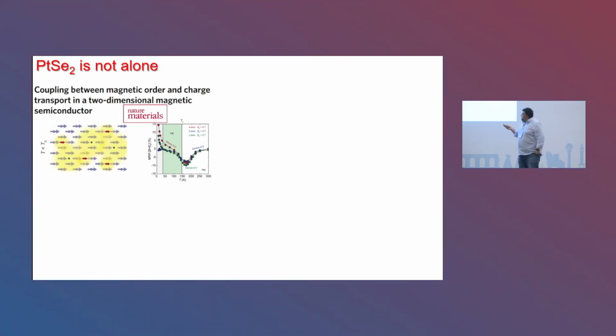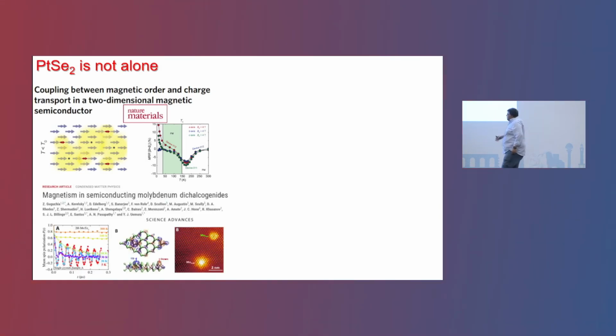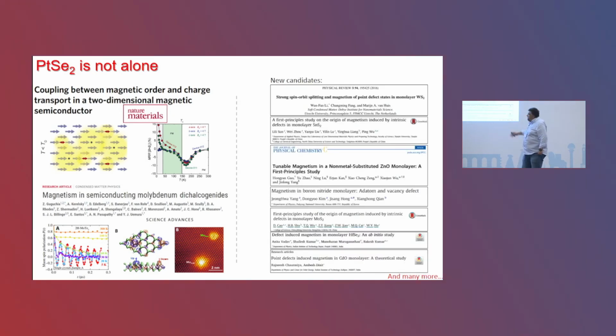One of them, for example, which was just published 2-3 weeks ago, is chromium sulfide bromide, which again shows this kind of defect-induced magnetism. There was also another study on molybdenum ditelluride, which was also showing defect-induced magnetism up to 100 Kelvin. And we have lots of new candidates, and lots of new predictions are happening that if you have these ultra-thin materials and create some defects in them, you can turn many of these non-magnetic materials into magnetic ones, and some of them are even layer dependent. The magnetic properties depend on the layer.